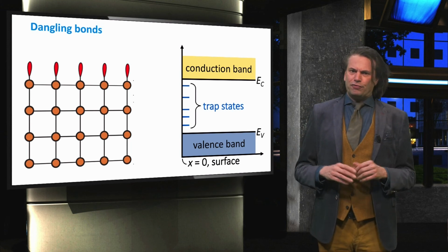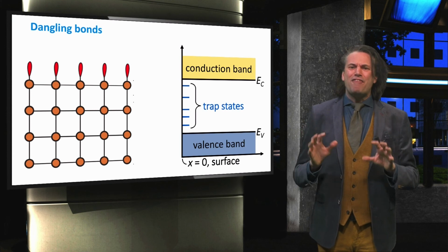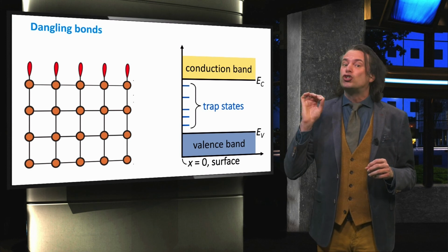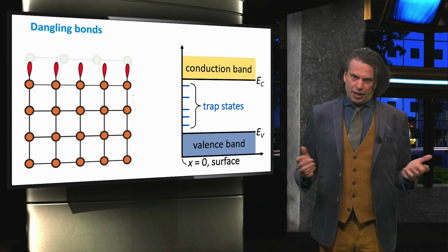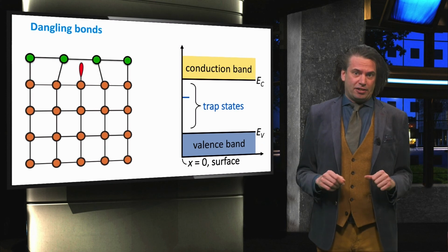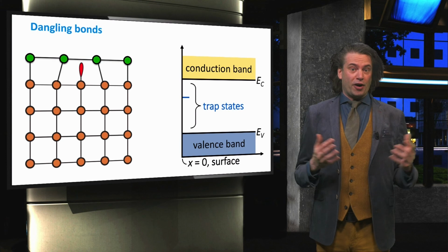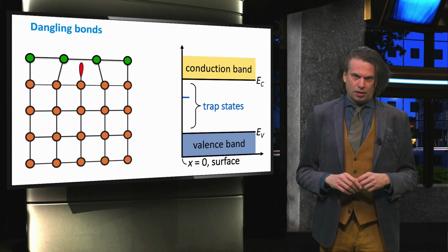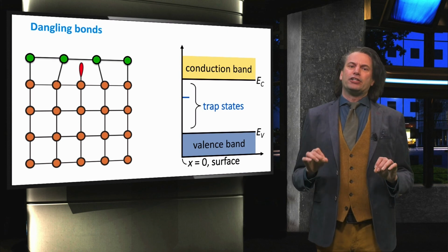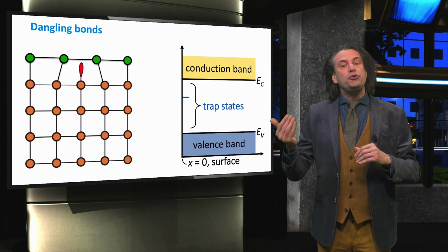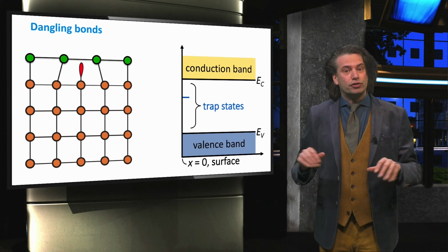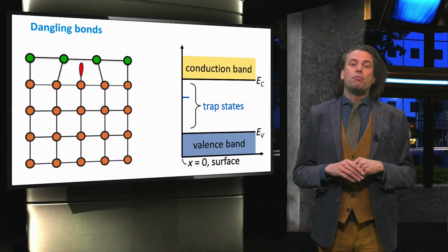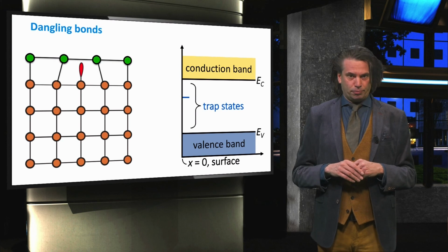In fact, for semiconductors that hardly have any defects in the bulk of the material, the recombination might be dominated by surface recombination. These dangling bonds are also present at interfaces between different materials, for instance because the lattice of the two materials might be mismatched. However, making an interface with another material might reduce the defect concentration at the surface. An indicator of the total recombination is the recombination current density, J0.